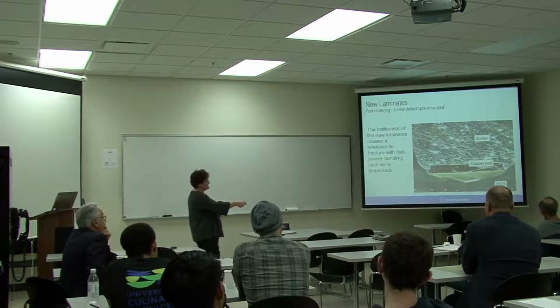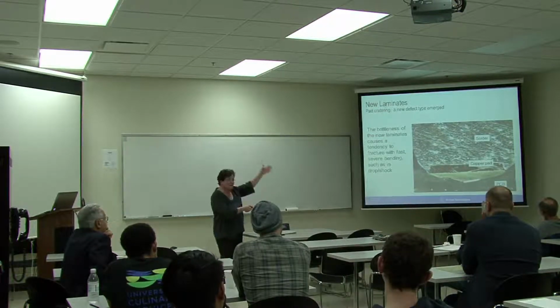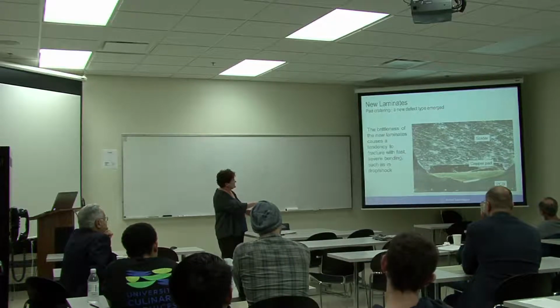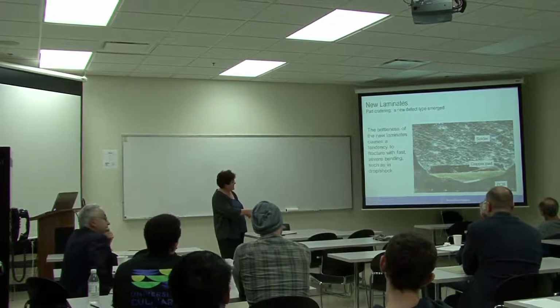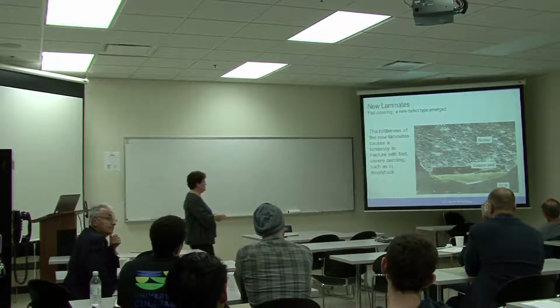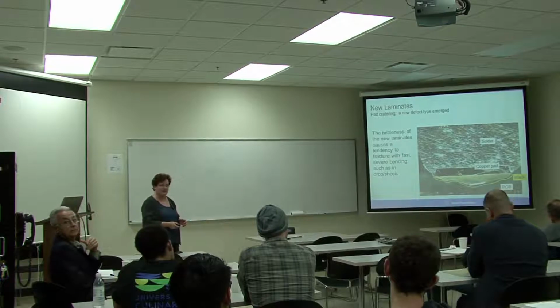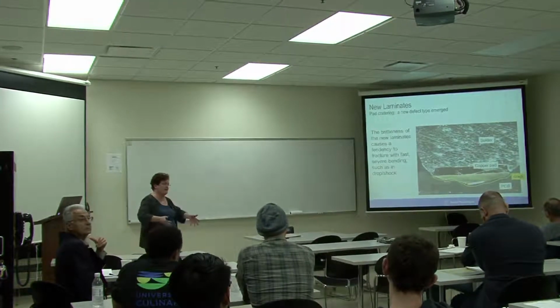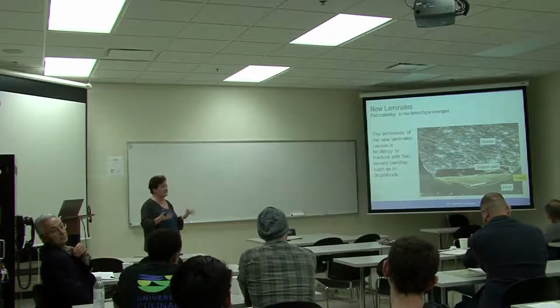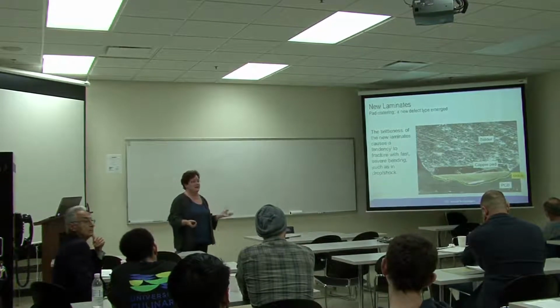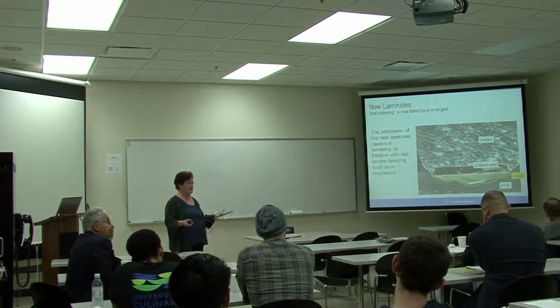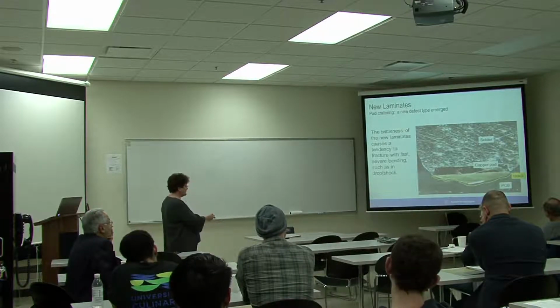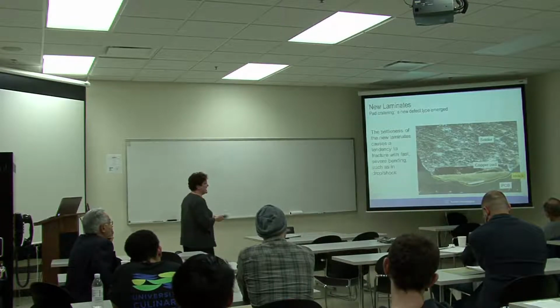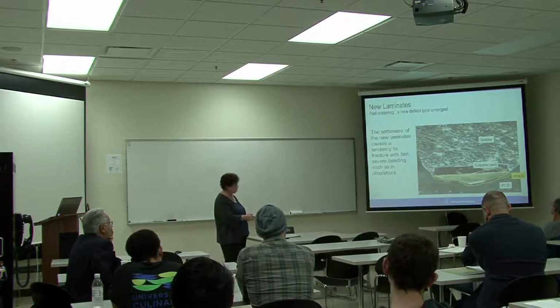So let me explain things. This is another cross-section. This is another one of those balls in a ball grid array. Here's the solder, there's the copper pad on the board, this is the raw board itself. And there is a fracture in the laminate that was caused by a drop test that was done. We do a test that basically makes sure that if the product falls off the truck, it won't die. So this was something that we found that for certain laminates, for certain ways that we had the parts on the board, we would have this kind of problem.